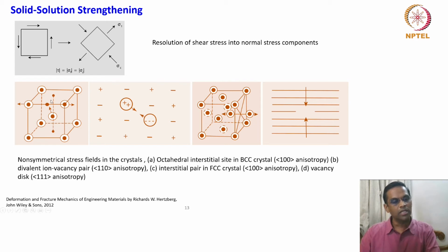The question is whether these octahedral sites are of similar size or not. They are not. The one which is in the edge is typically in the order of 0.038 nanometer. The one which is in the face center is in the order of 0.156 nanometer.